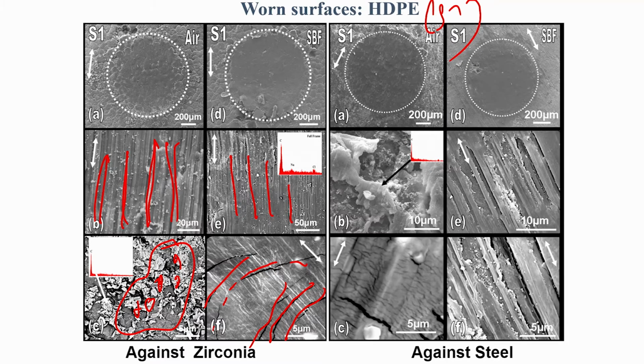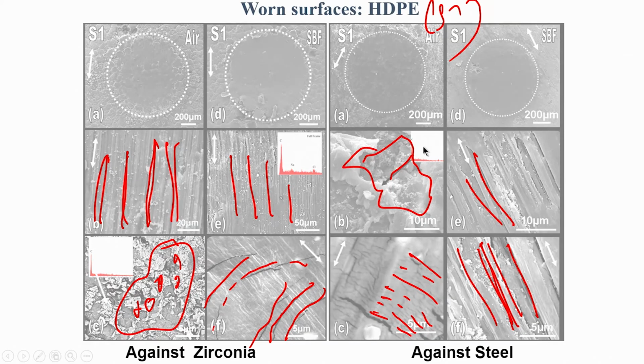Now, what happens in case of steel? Since the wear rate is higher, you can see much deeper abrasive scratches, and if you look at some of these deeper abrasive grooves, there are signs of abrasion and also cracking observed. Like in the previous case, we have seen micro cracks coalesce together to form concentric cracking in the ambient conditions.